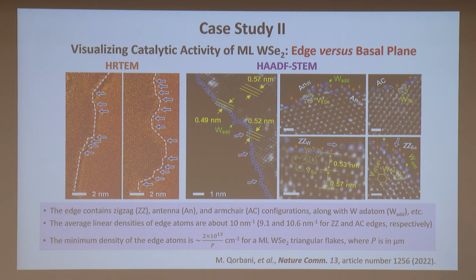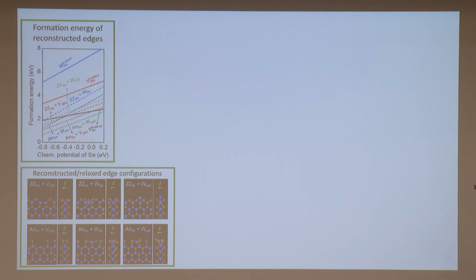Now, if we produce the layer in a sort of scattered island, under optical microscope they are straight on the side, they are regular shapes, but under TEM, none of them are straight enough. They are always mountains and valleys, and if you analyze more carefully, you have the zigzag shape, you have the antenna shape, you have a lot of different reconstructed edges, okay? And the number density of the defects could be quite high at this level. So all these do have some formation energy. Apparently some of them are so easy to form the defect type as shown here.